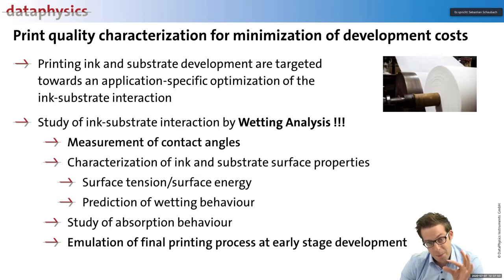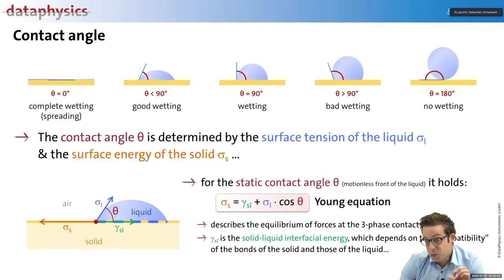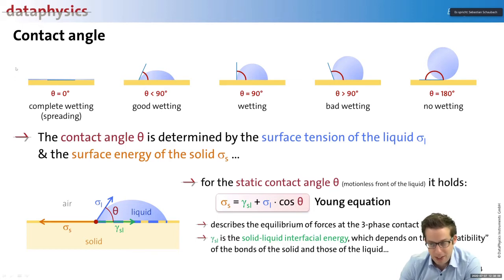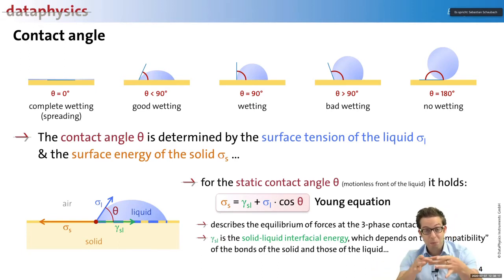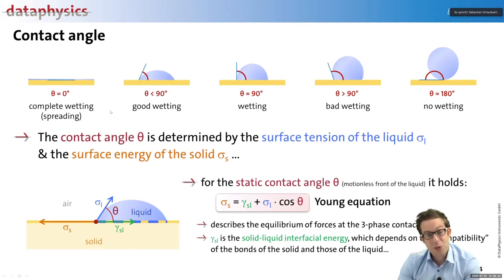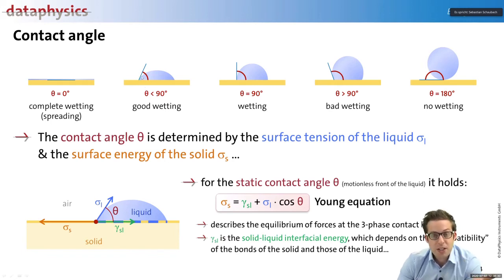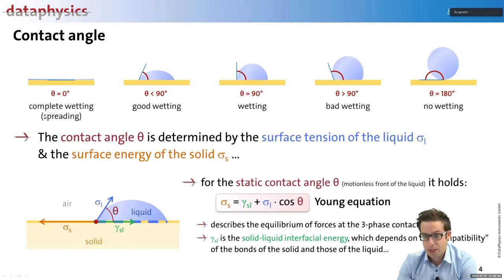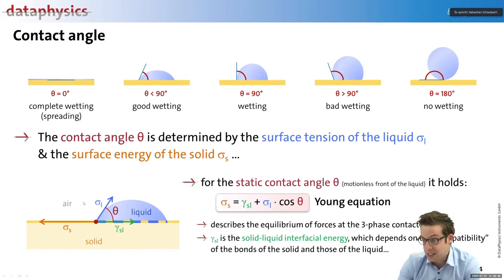You can also make a test print and see whether it's working. On contact angle measurements in general: when you jet a drop on a surface, you can get complete spreading — we don't want this because the picture is not clear — or bad wetting, which we also don't want because you use a large amount of ink to cover only a small surface area. Contact angle measurement teaches you which liquid-solid combination gives ideal wetting, which is around 20–30 degrees, using a really low amount of liquid without complete spreading and blurring.